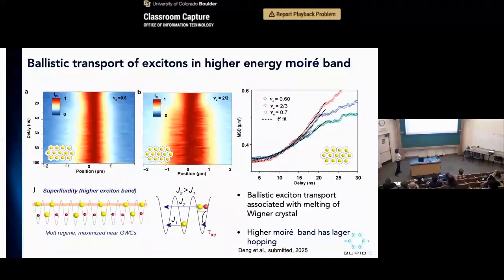And we can look at this transport more closely. So if I just look at one right below the 2/3 filling, and one right at 2/3 filling. And again, this is time, this is space. You can almost immediately see that when they are at this critical filling, where the electrons are forming a crystal, the excitons spread out much faster.